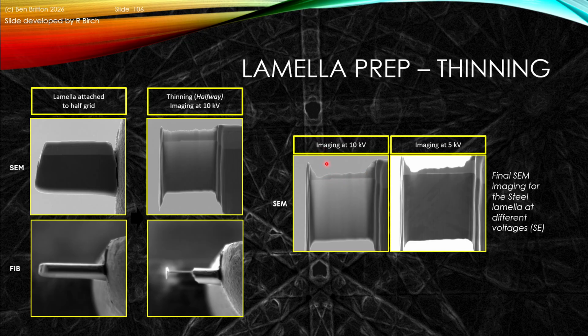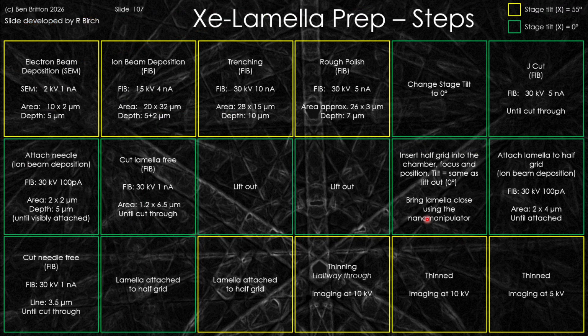And when we image this at 10 and 5 kV, we can start to use two different voltages to establish whether this sample is interesting, and so effectively whether the sample is sufficiently thin to reveal contrast. And you can just about see the presence of contrast, which is the different, effectively bainitic or ferrite-like laths within this material. To do this in practice, this is showing us the different steps.